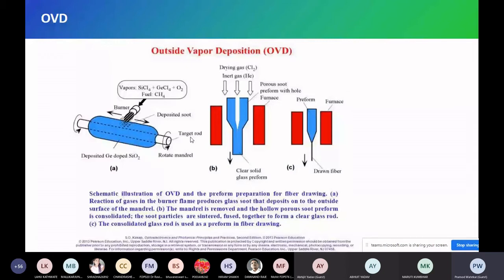I will show one picture. It will be very clear to you. So we send our gases. There is a burner, and an interesting thing, we have a burner. Through the burner, we send these gases. Okay, so heating and deposition is taking place at the same time. So we deposit such type of things. Then we take this soot, it's a big size soot, and put it in the furnace. We heat it again at 1700, and this soot now gets consolidated into glass because now the temperature is very high. So slowly it becomes glass. Size reduces, and we get the glass. It is called OVD glass.